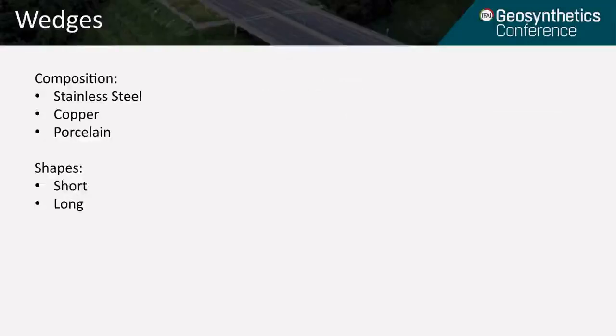As I mentioned, wedges can come in different material compositions such as stainless steel, copper, and porcelain. The use is dependent on the material. Copper is going to give you your most uniform heat transfer, but it's also going to react with PVC, so it's not a good choice for PVC. There's also different shapes, such as a short and a long wedge.